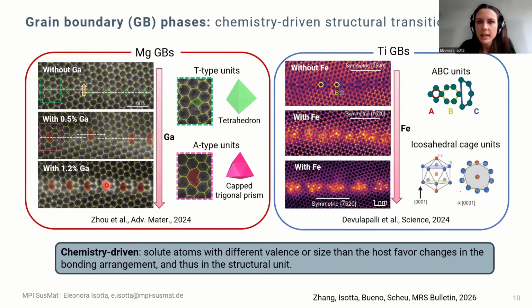A similar type of structural transition was also observed in titanium alloyed with a little bit of iron, because it was really observed that with the increasing amount of iron, increasing concentration of these icosahedral cage units tended to form at the boundary.